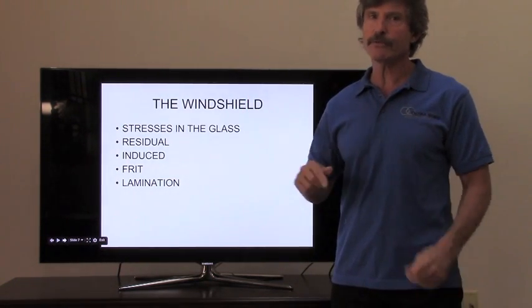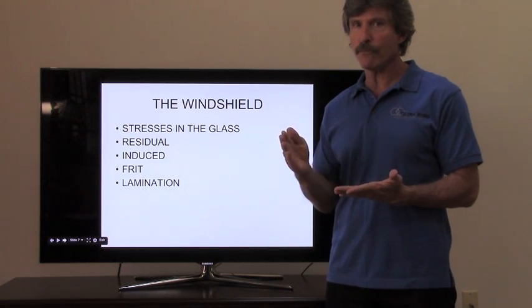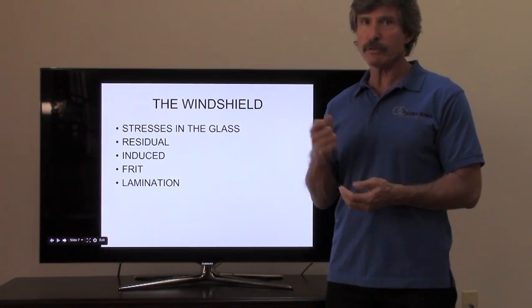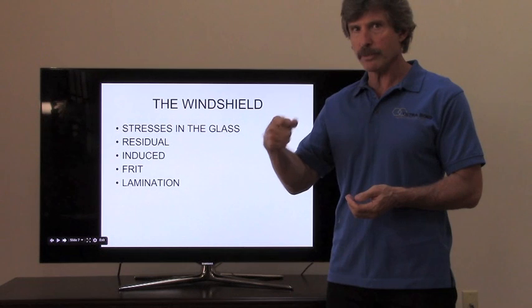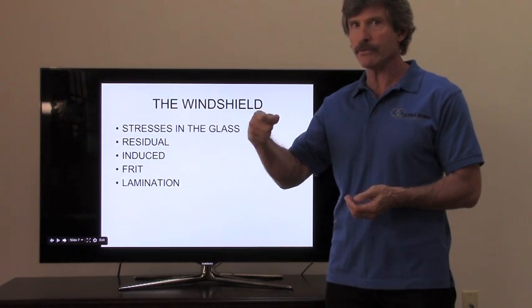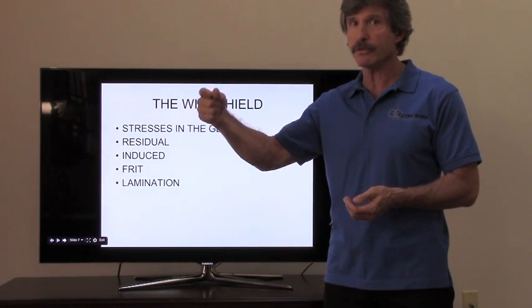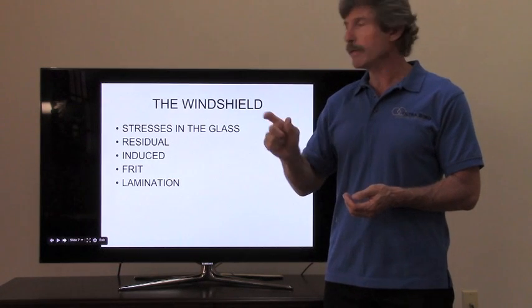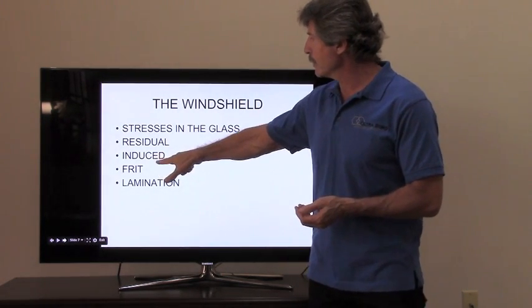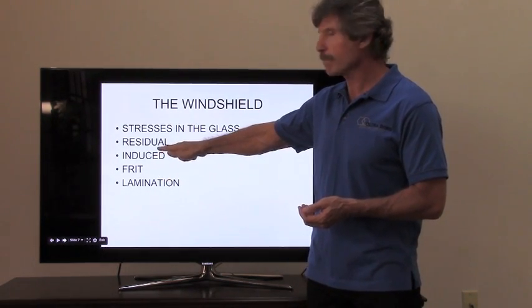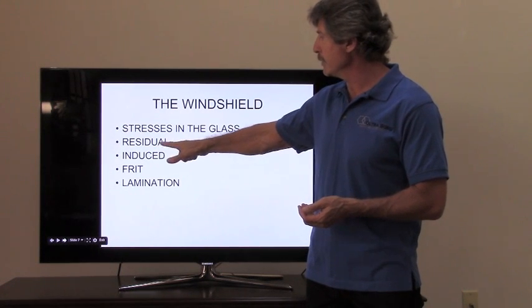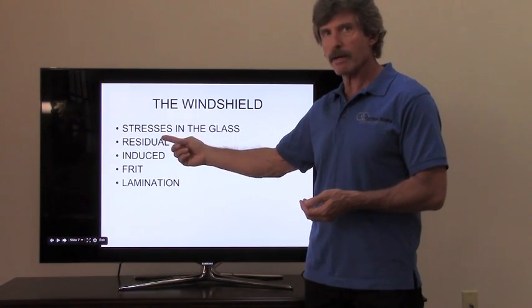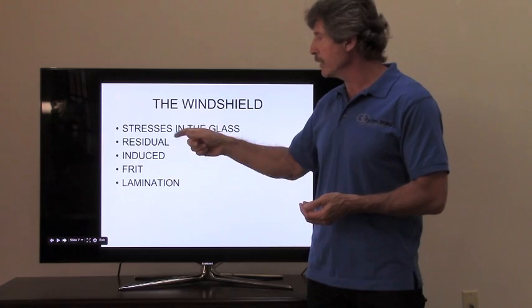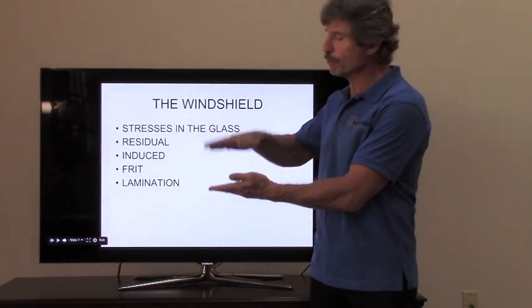You can feel that stress. It goes out about 4 inches. If you go out to your windshield and take your knuckles and knock on the edge of your windshield, you'll feel how tight it is until you go out around 4 inches, and then it'll start feeling hollow. That induced stress causes an impact or a chip in the weak spot to crack immediately. And this is also what causes the crack to split open.